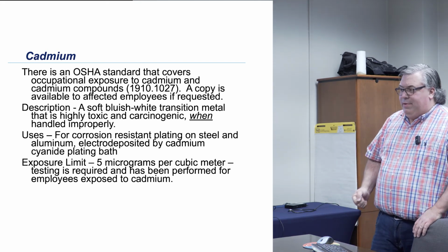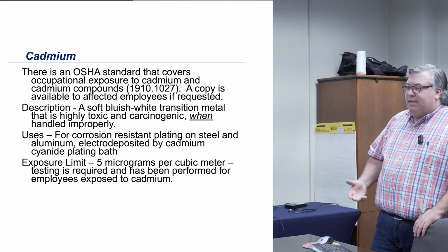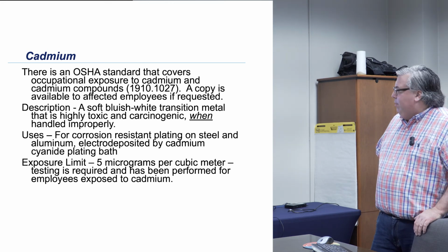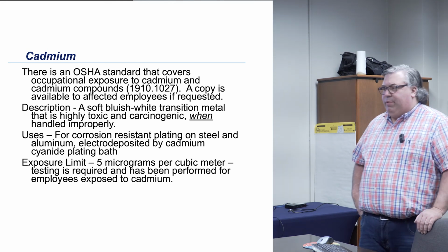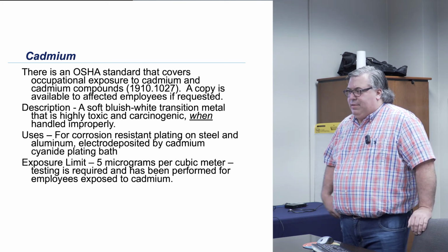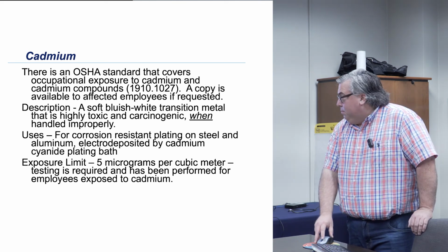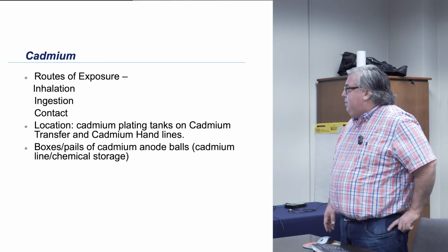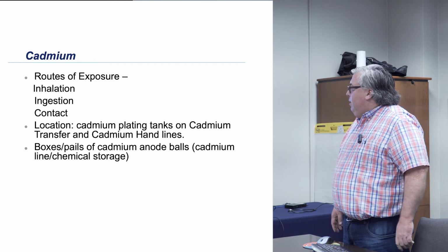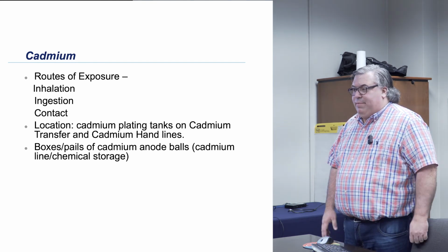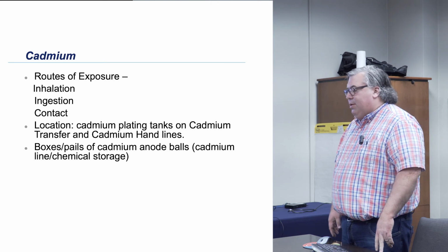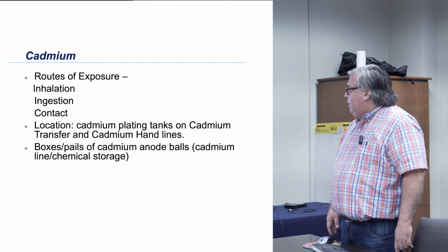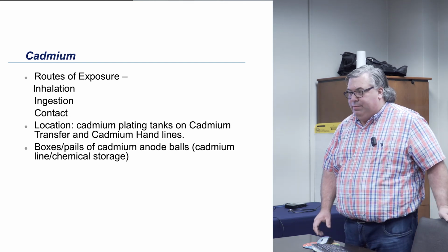The good news is cadmium doesn't get in the air very readily. We've actually tested twice now at Co-op, and we were well below the 5 micrograms. We were in fact at undetectable limits of cadmium in the air. Routes of exposure, all 3 of them: inhalation, ingestion, and skin contact. Cadmium is in the cadmium plating tanks. There are also cadmium anode balls that are generally in the chemical storage area.